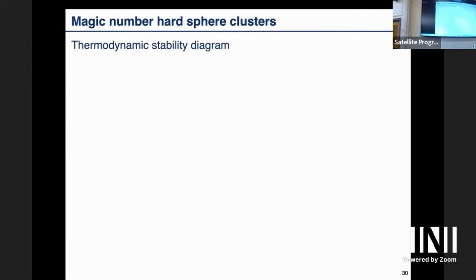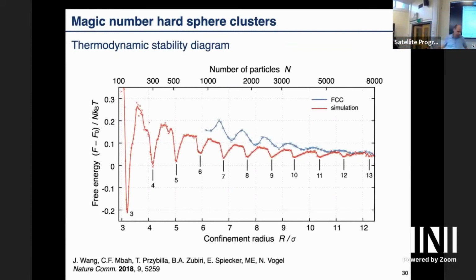Namely, we can do free energy calculations of these clusters. So we wanted to get a diagram which looks like the mass spectrum, where we see certain diameters are more stable or better than others, to really argue they're also really thermodynamically magic number clusters in our system. So we did free energy calculations. This is not simple for these clusters because the cluster is only partially ordered, and also because it's a relatively slow evolving system. So the free energy diagram that we ended up showing took us probably 2 years to do the calculation.